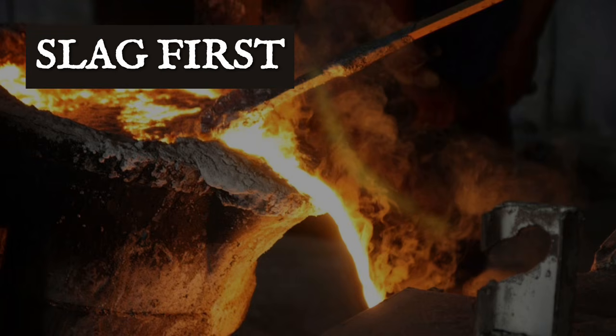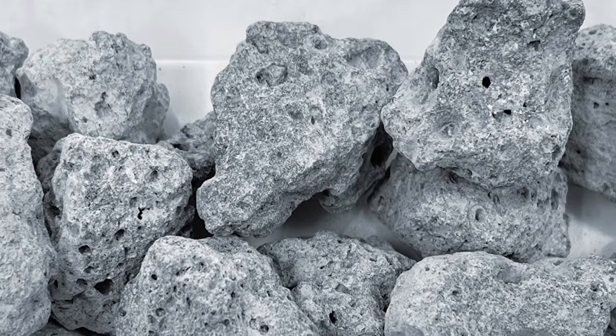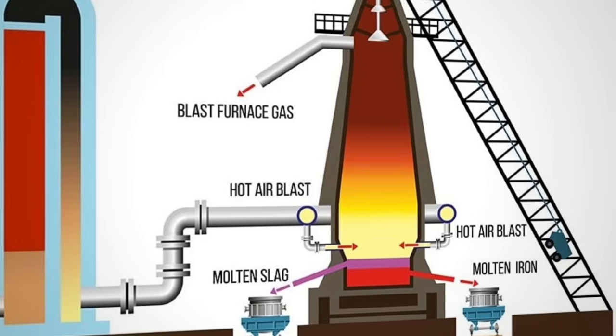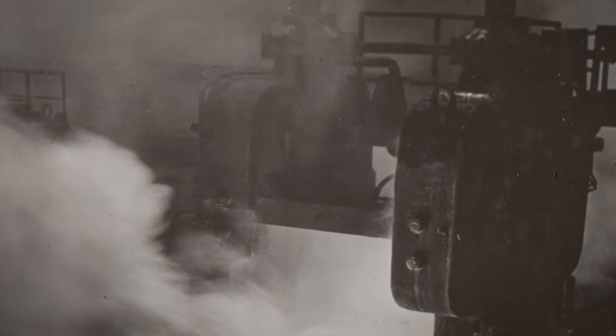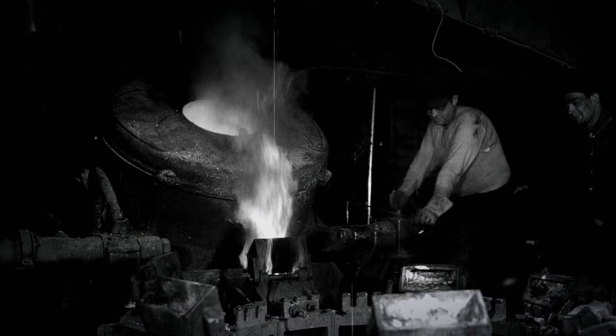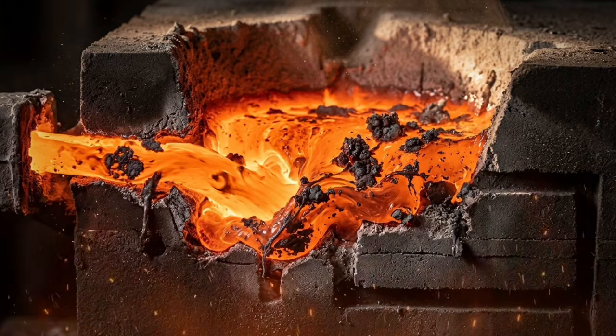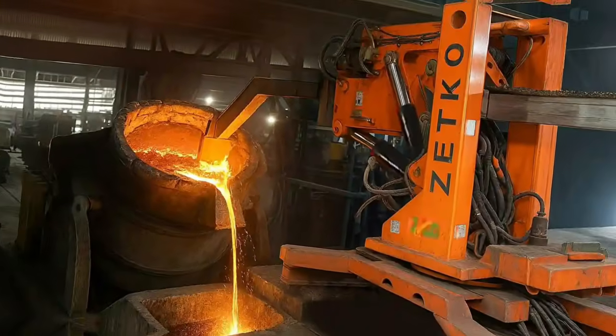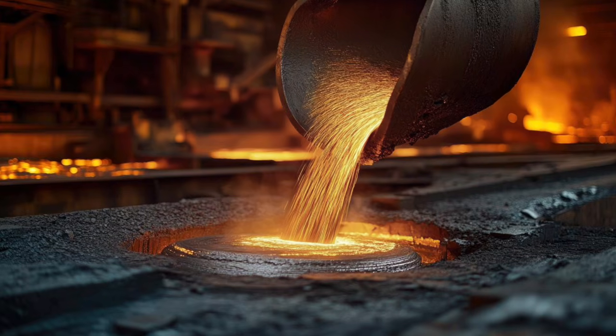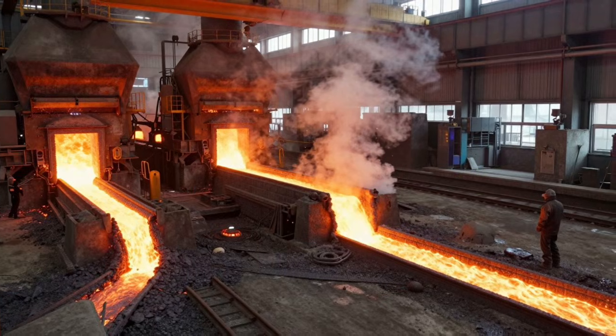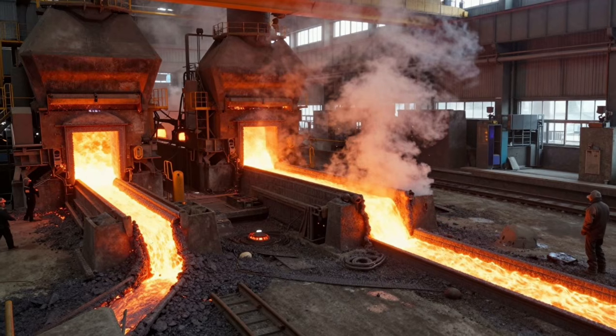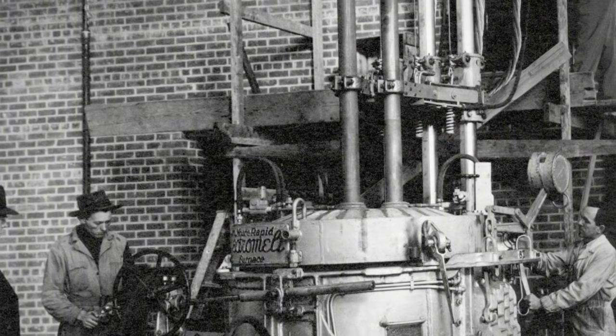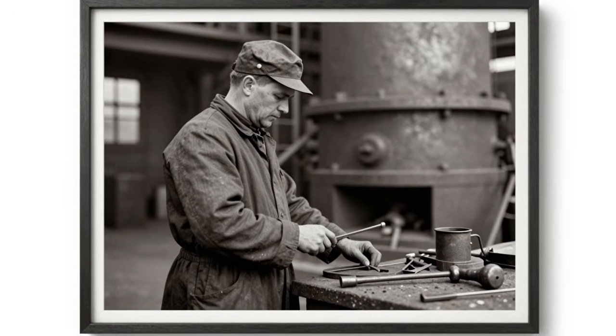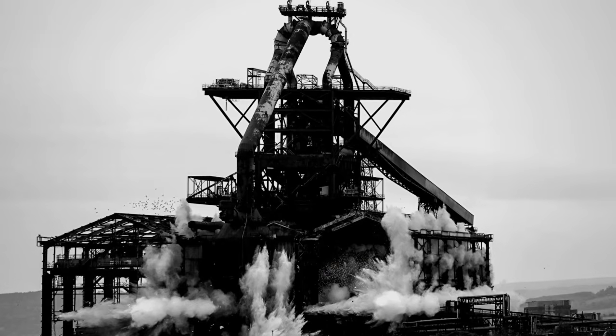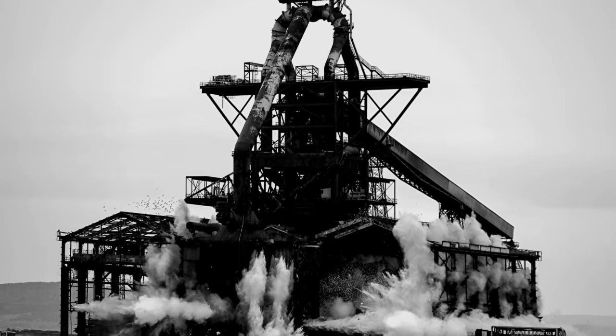Before the iron flows, the slag must go first. Slag is the lighter waste material that separates from the iron during smelting and floats above it in the hearth. It exits through a separate opening higher on the furnace wall, called the cinder notch, before the main cast begins. Slag is liquid stone, lighter than iron but nearly as hot. A slag runner that fails to seat correctly, or a cinder notch that opens unexpectedly during a cast, puts liquid slag on the cast house floor simultaneously with liquid iron. The keeper manages both sequences. This is another reason the job requires specific knowledge of this furnace rather than general knowledge of furnace work.